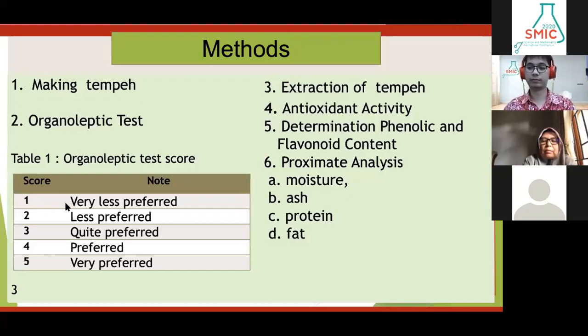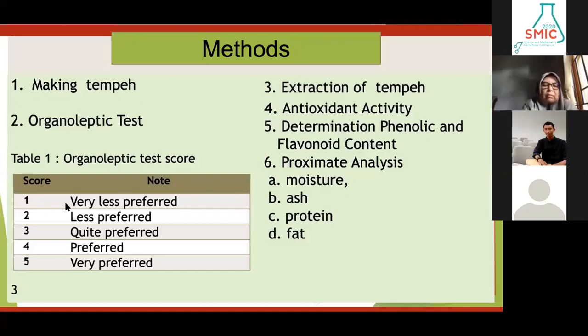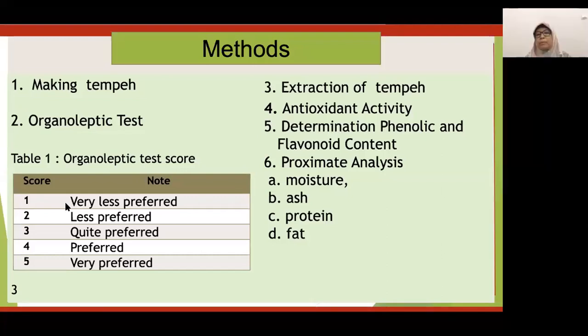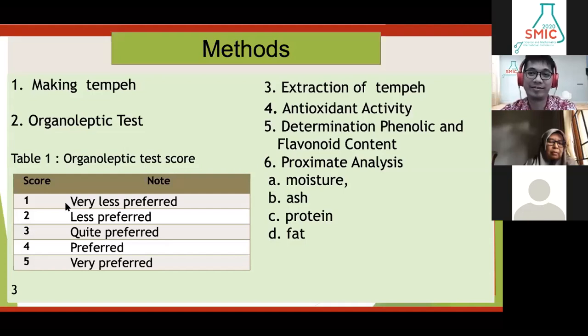Antioxidant activity test. We dissolved kidney bean tempeh extract using methanol. Then the extract was made as a series of 500, 250, 125, 62.5, and 31.25 ppm. 2 ml of this sample was added to 2 ml DPPH solution and then incubated for 30 minutes. The absorbance of the sample was measured by spectrophotometer and then we calculated the IC50 value.